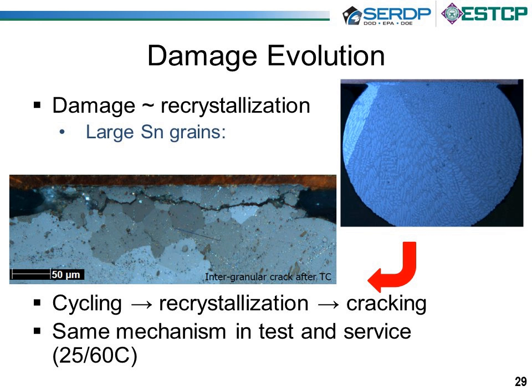Okay, so that's the next part of our deliverables in this. And then we pretty much have, what we said, the expressions for the deformation properties and the materials properties. And what we need now is to say what happens in terms of damage. When we talk about damage, we have to look at how damage happens in the lead-free solders. And if you look at the top right here, you see a cross-section of a typical solder joint. And in slightly different colors, you can see different orientations of the tin grains. So you can see there's like three large tin grains in this joint. And they're sort of special, but I'm not going to get into that. But the point is we got very large grains.